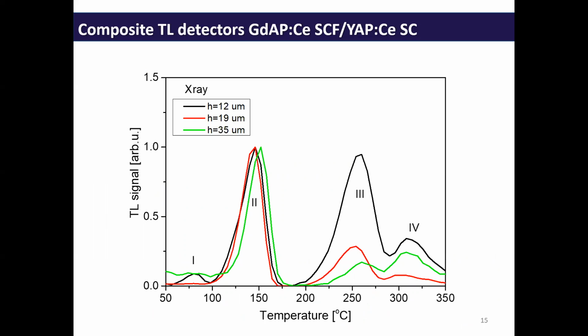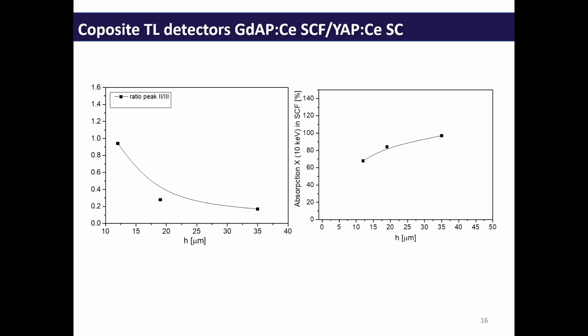The signal from X-ray analysis comes from the layer and from the substrate. If we look at the green curves from the layer with thickness of 35 micrometers, where the absorbance is 97%, it can be said that regions 3 and 4 for this sample are actually only a signal from the substrate. We show some dependence and observe intensity decrease with thickness and absorption increase with thickness.